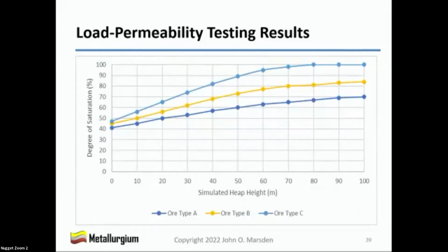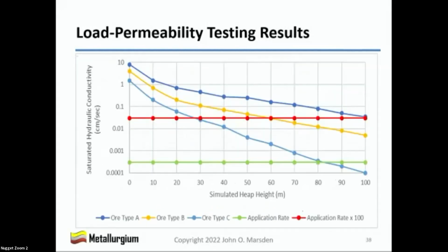So now if we go back to the first graph, you can see ore type B passes the threshold of 100 times the application rate at about 60 meters. By 100 meters, it is somewhere a little over 10 times the application rate. And that was a bit of a flag for Jack. He was not terribly excited about that. But alarmingly, ore type C gave a real problem. This was at 80 meters. He could not get conductivity at the planned application rate. So he had a big problem with ore type C.